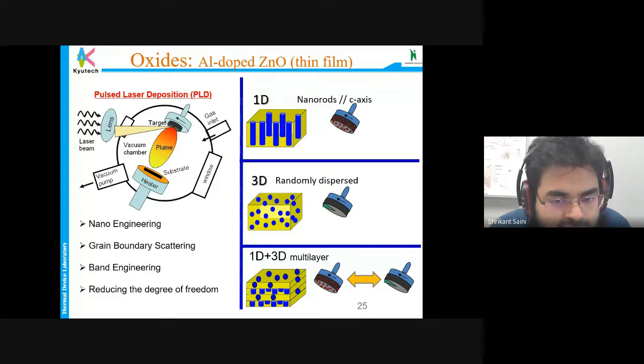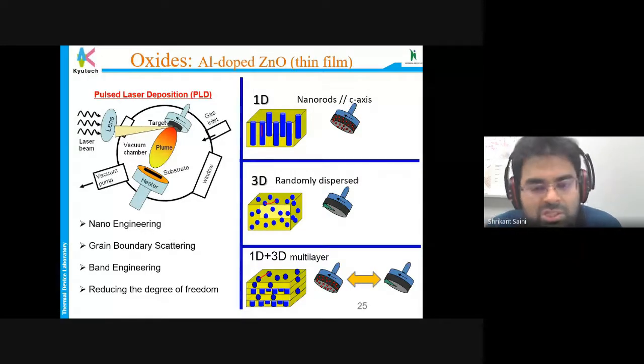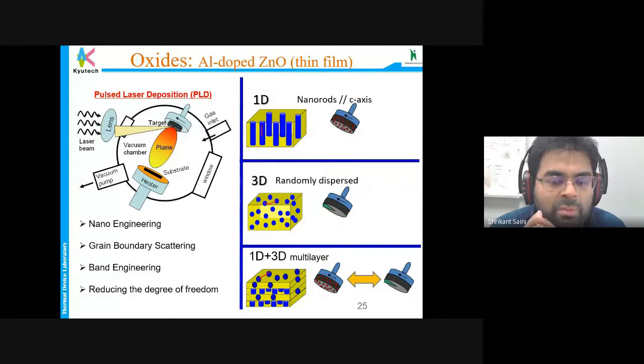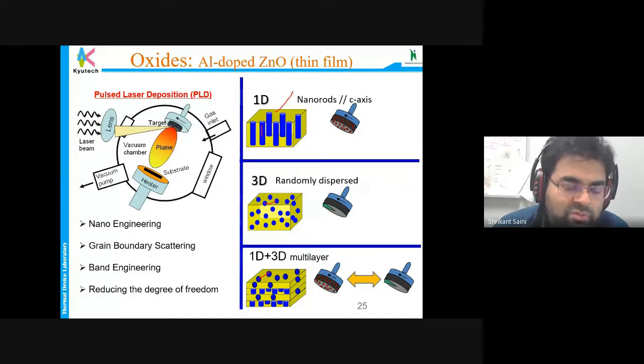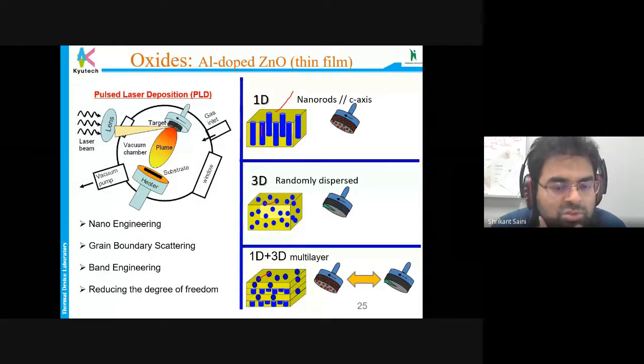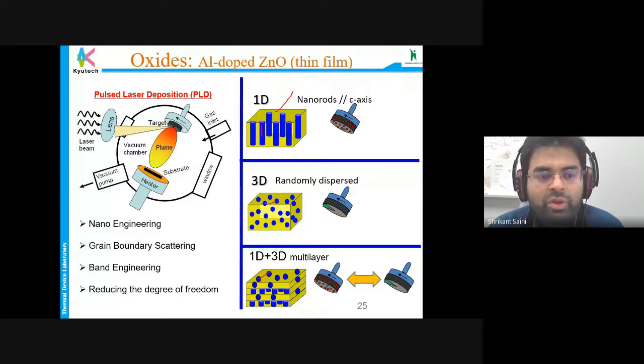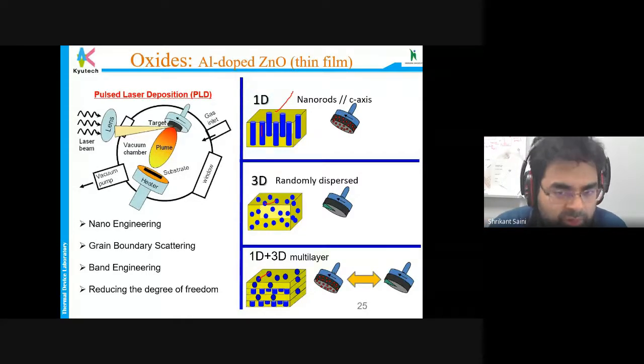Similarly, when we combine these two and work with two targets inside, we can achieve the film which is this. All these different kinds of structures work as phonon scatterers, plus they help you tune the band gap of the overall material, which is zinc oxide in our case. These approaches we have used, and they are easy to use when you make a thin film of this kind of material, rather than working with a bulk material. We have reported results where the thin film has achieved better results than the bulk material.